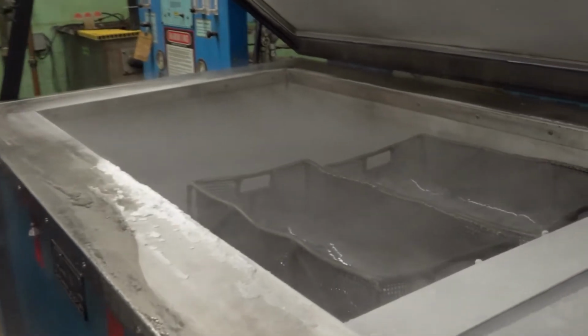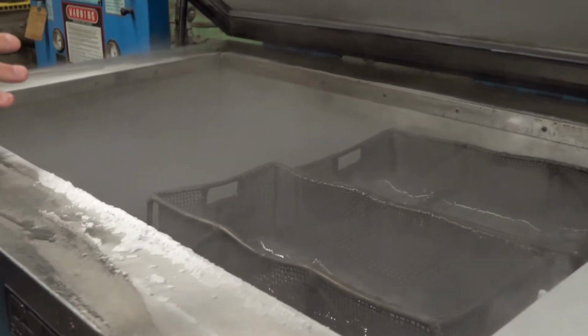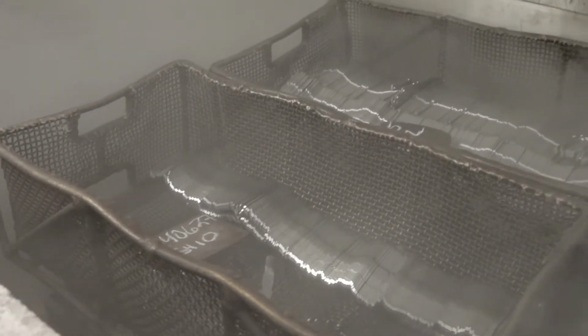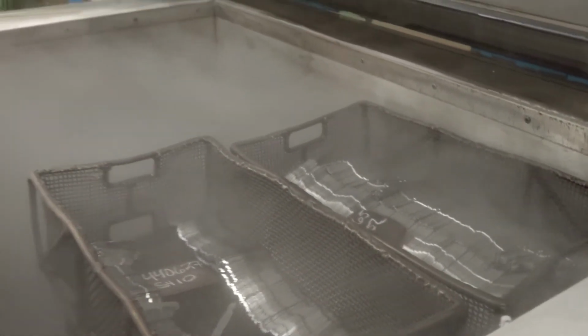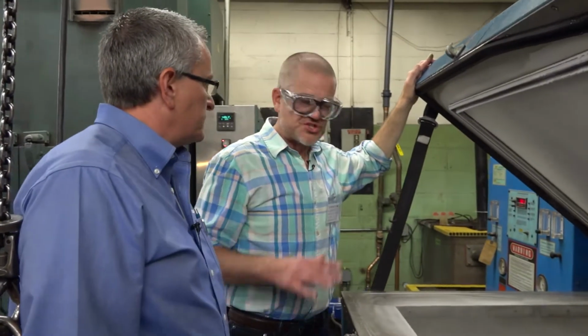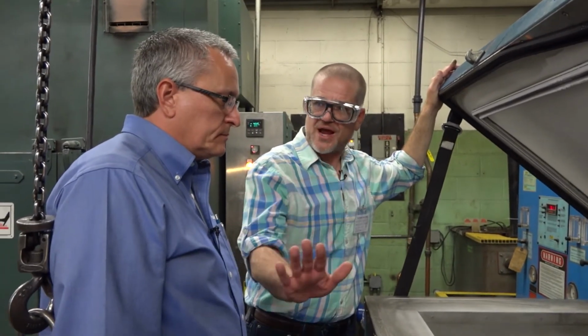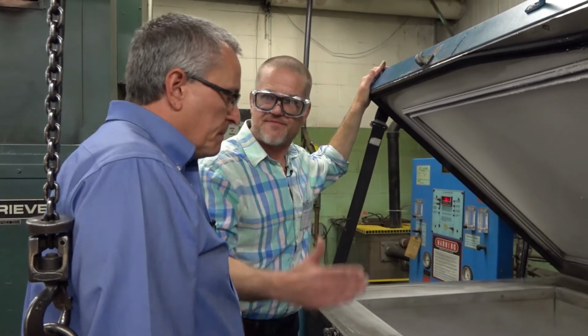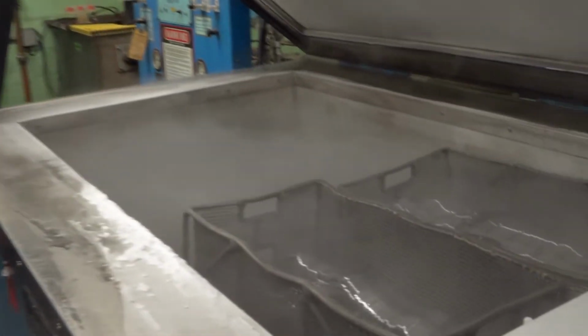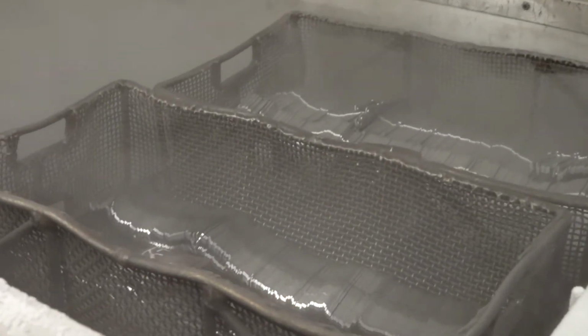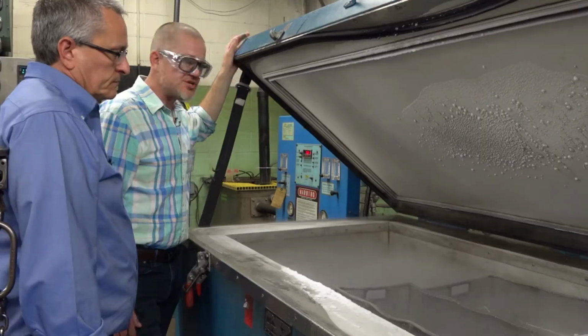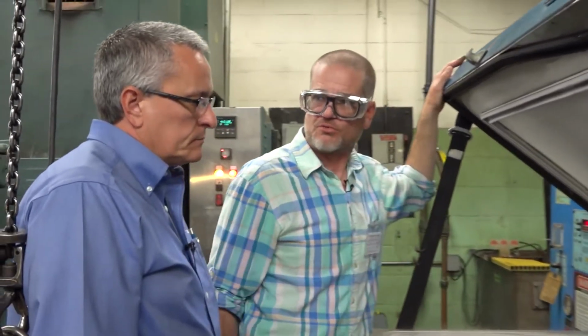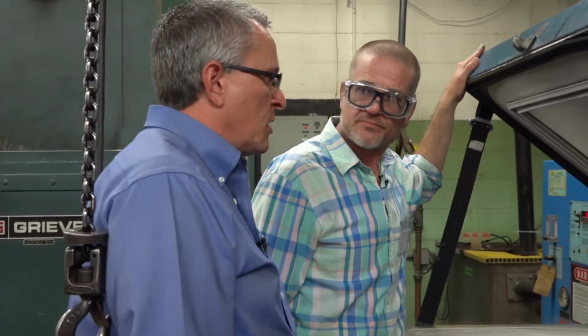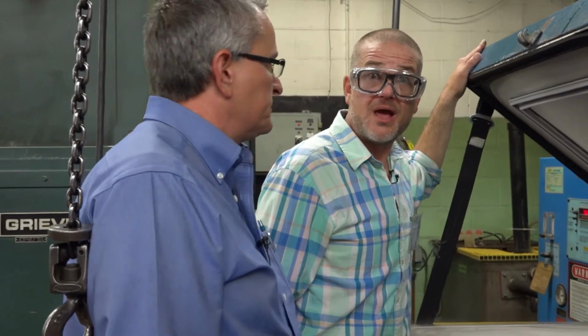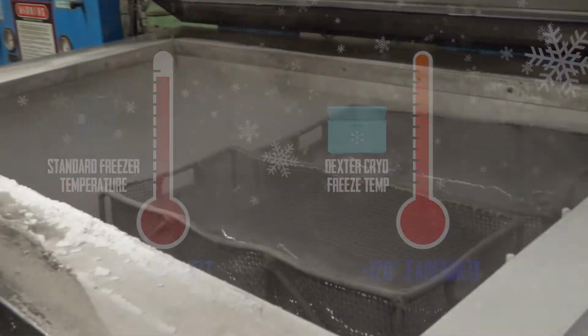So right now it comes out of the main heat treat furnace, and this is our cryogenic freeze where we're actually really locking in the elements in solution when it comes out of the heat treat furnaces. So this is a step that is going to strengthen the heat and quench process one step further. Yep, this is our extra process to make sure that everything was done just right in the heat treat process. And just a question, how cold is this compared to a regular conventional freezer? This goes down to a negative 120 degrees Fahrenheit. Negative 120. That's cold.